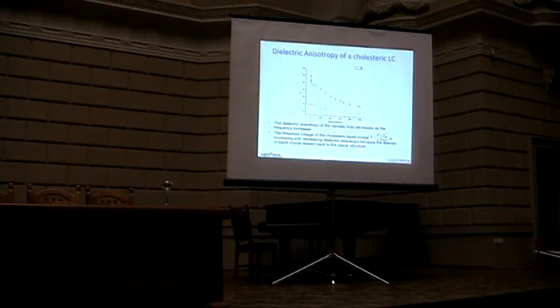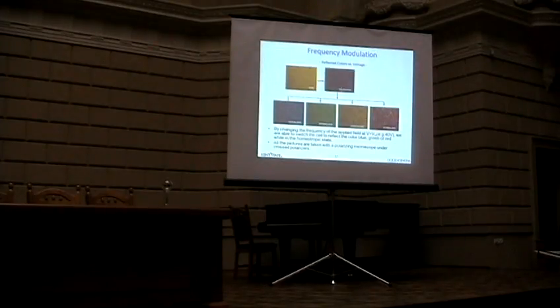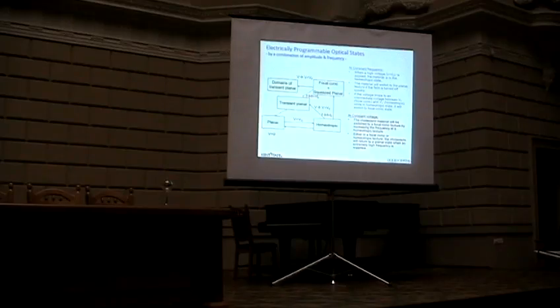On the other hand, these materials respond to the frequency of the applied voltage slightly differently, depending on the dielectric anisotropy. You see a shrinking of that range as you increase the applied frequency. So, in general, with that kind of characteristic, you can also use the frequency to tune these colors. You can change from blue to red or red to blue by applying a different voltage or frequency. So that allows you additional methods to program the optical tuning of the colors.